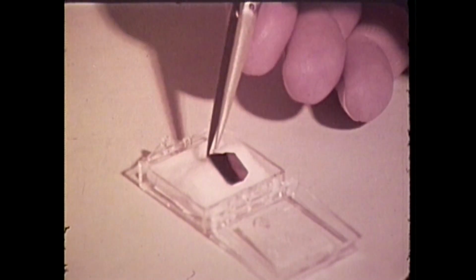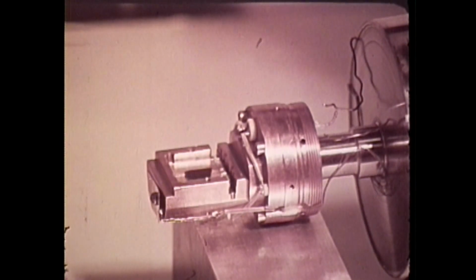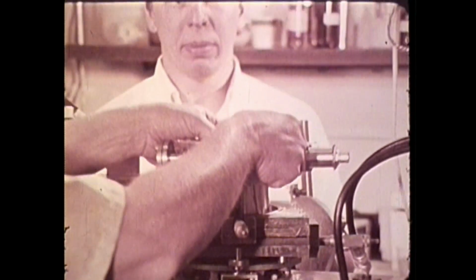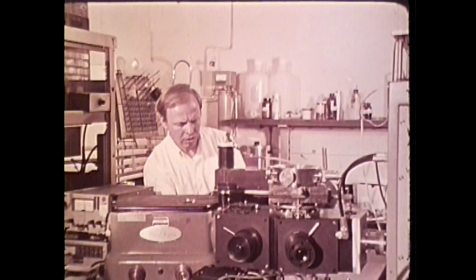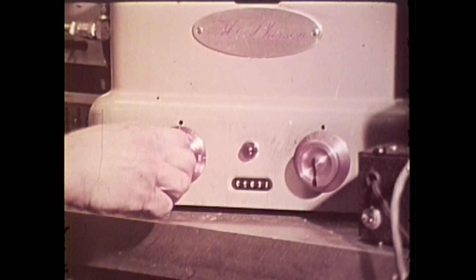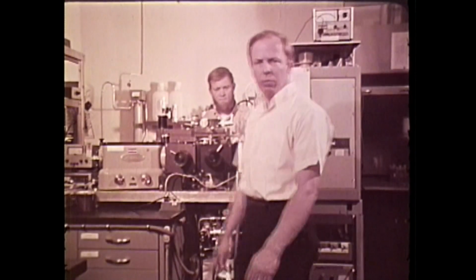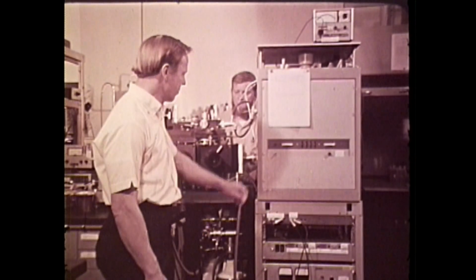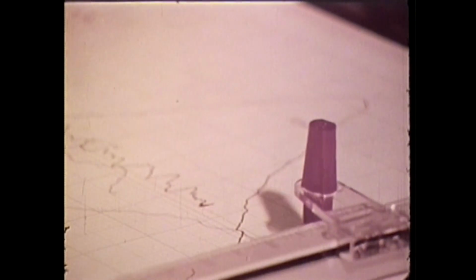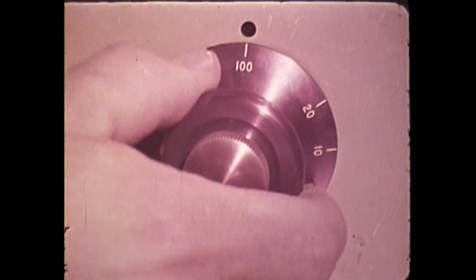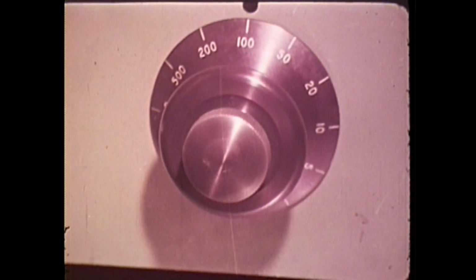A sample of semiconducting material formed into a smooth mirror is placed in a high vacuum cryostat. The sample is then positioned in the light path from a scanning monochromator. This produces a beam of controllable wavelength from infrared through ultraviolet. We then apply a strong alternating electric field across the sample. The reflected light is detected and analyzed in two parts, one modulated by the electric field, the other constant. These are then ratioed and plotted against the wavelength of the incident light. The experimental setup is sufficiently sensitive to detect a change in reflected light intensity caused by the electric field as small as one part per million. Results have verified the one electron band structure approximation in greater detail than ever before.